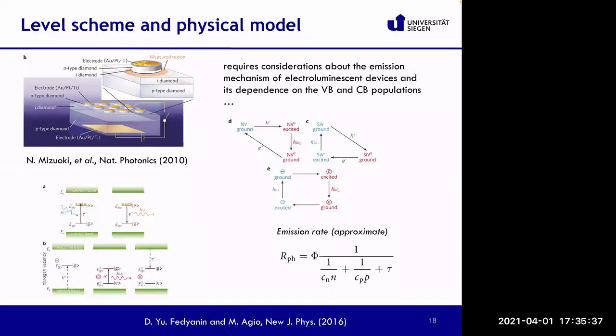But anyhow, in this case, you have a completely different process. So you see in the picture below the difference between photoluminescence and electroluminescence for the nitrogen vacancy. In panel A, you see the valence and the conduction band of diamond, and in this band gap, you place the energy states of your nitrogen vacancy or silicon vacancy, let's say. So you see that these states very much resemble the two-level system that I described before. So you have the ground and excited state. Under optical pumping, you come with a photon, and this photon brings an electron to the excited state, and then you have the spontaneous emission, which generates a photon. And this is a single photon source.